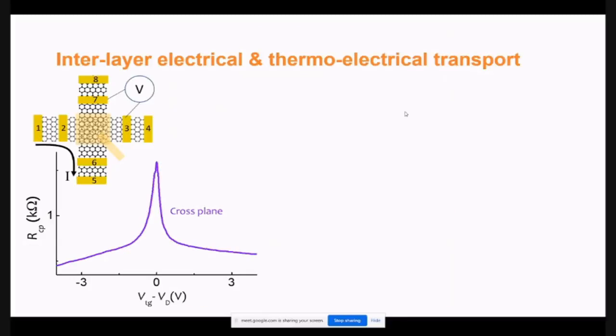So let me tell you how the electrical properties look. We are talking about cross-plane electrical properties, in which this is one layer and this is the second layer. I pass current from the upper layer to the lower layer and measure the voltage between them. So it's an electrical property. This voltage essentially drops between the two layers, and that gives us this R cross-plane. I know the current, I know the resistance, and as you apply the potential, this goes down on both sides, because this overlap region is getting doped by the top gate.